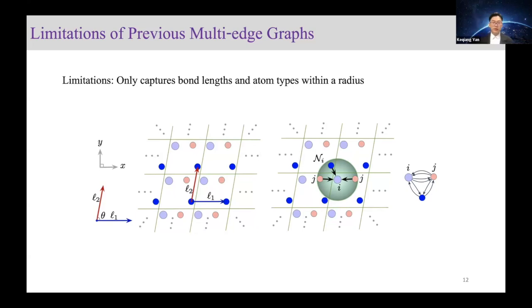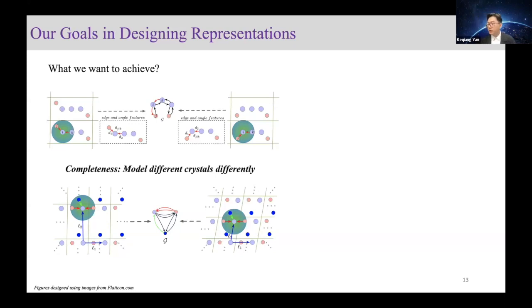Let's begin from the previous widely used multi-edge crystal graph proposed by CGCNN. As we can see, for sure, it can capture the local interactions within a radius for this given light blue node, but it only considers bond lengths and neighboring atomic type information, and it is not complete and has a lot of limitations. From our side, we actually want to build representations to be powerful, robust, and equivariant. The first thing we want to achieve is completeness. We want to make sure the AI algorithms can distinguish any different structures and do not map different structures to the same representation, which is totally wrong. Here, I show two cases that a previous multi-edge crystal graph will fail to distinguish. As we can see on the upper part, on the left hand and right hand side, there are totally different structures, but the graph will be the same.